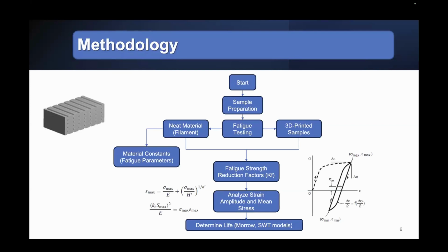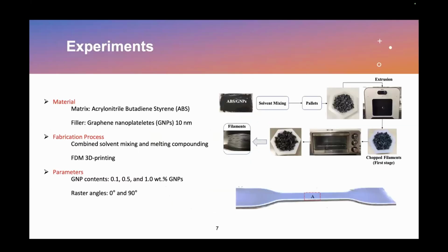From the fatigue test data of filaments, we can extract material constants like fatigue parameters, strain-based fatigue parameters, and using fatigue data of filament and 3D printed samples, we will be able to find fatigue strength reduction factors. And then we can analyze stress and strain in the notch sample using both Ramberg-Osgood and Neuber equation. And then after that, we will be able to determine life using modified Morrow or Smith-Watson-Topper model.